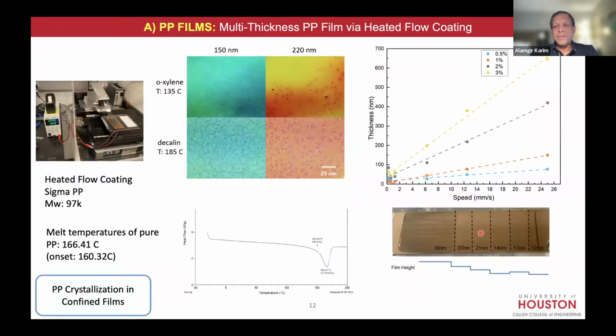Just to give an example, this is what the film looked like, film height. This is the thickness as a function of the speed of flow coating. This is called a flow coater, where we drag it at different speeds. Point is, we have very nice linear behavior. So this is the different concentrations going from low to high and different speeds. The combination of solution concentration, with one concentration, you'll make one set of film, like the blue. Increase the concentration, you make the orange. Okay, so this is how you make, it's called the high throughput approach. Then you can study, of course, the DSC properties and so on. Everyone may know that, the melting point is about 166 in this case, as you can see from the DSC endotherm.